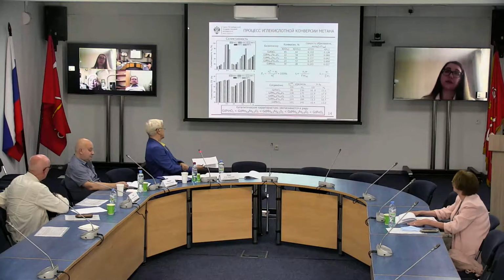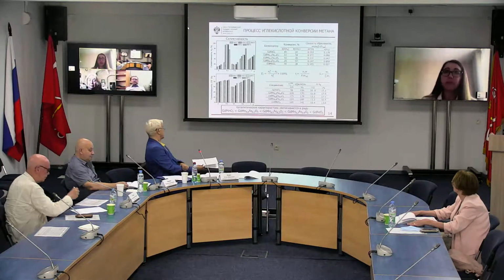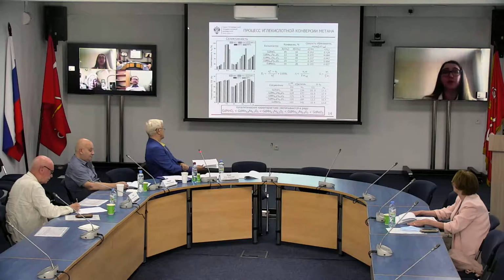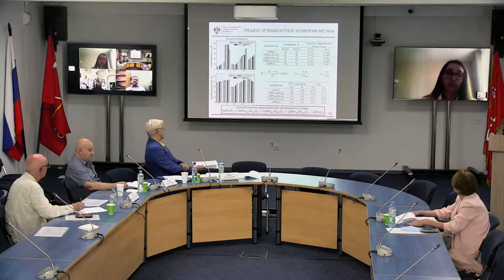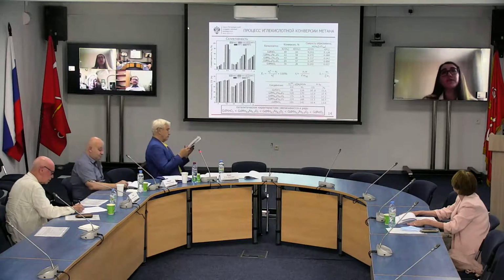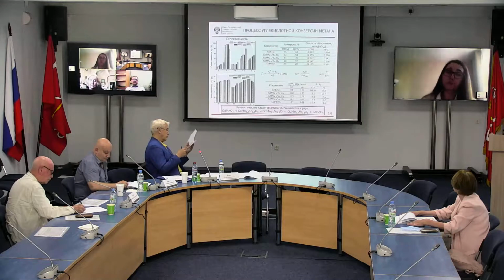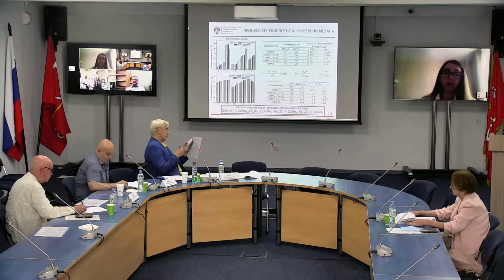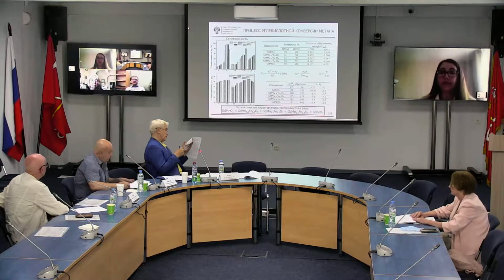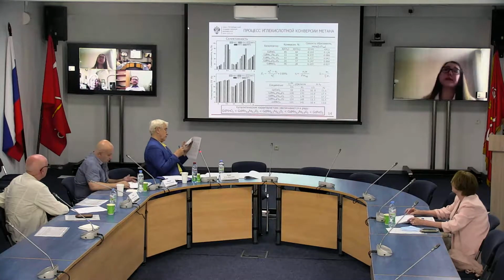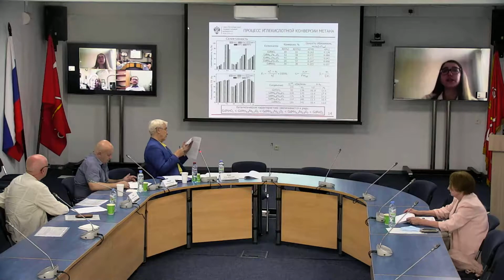And also our assessments show that the introduction of manganese and the formation of solid solutions lead to the growth of energies of activation in product formation, and at that, logarithm values were higher in solid solutions than in ferrites and manganites of gadolinium. And the drop of speed of formation of hydrogen and CO can be explained by the energy factor and also by differences in coupling energy.